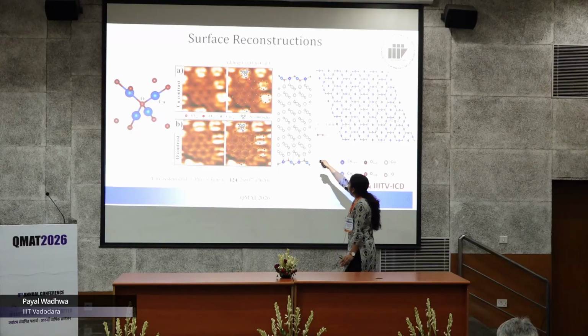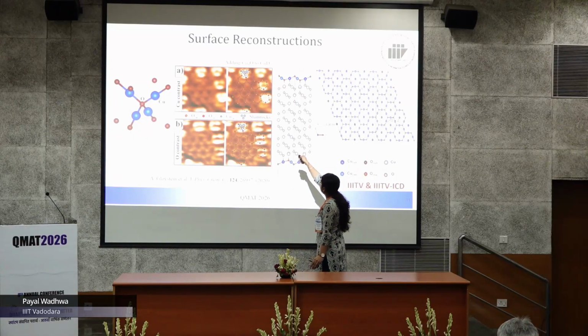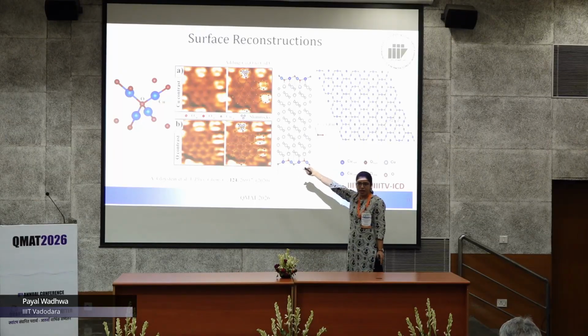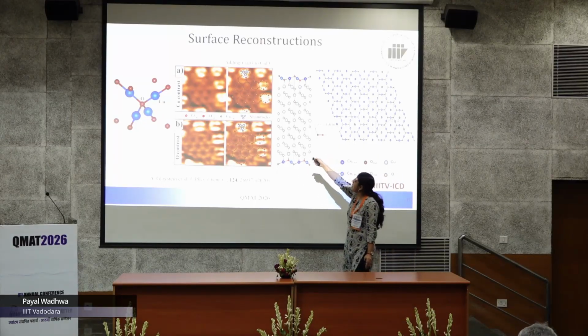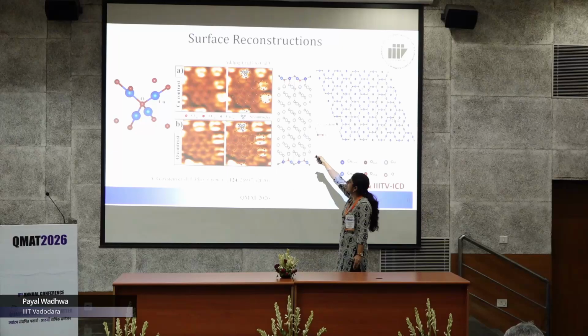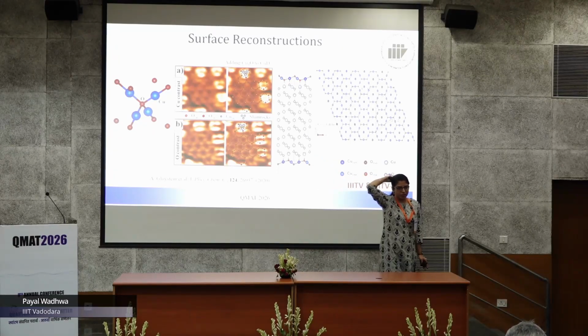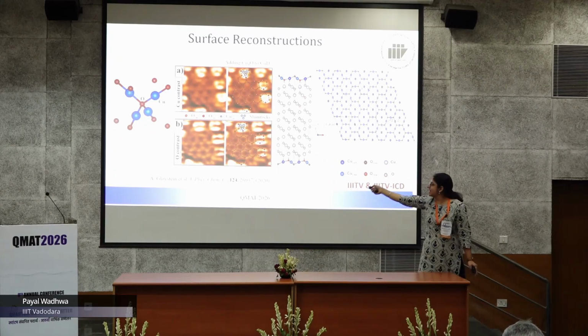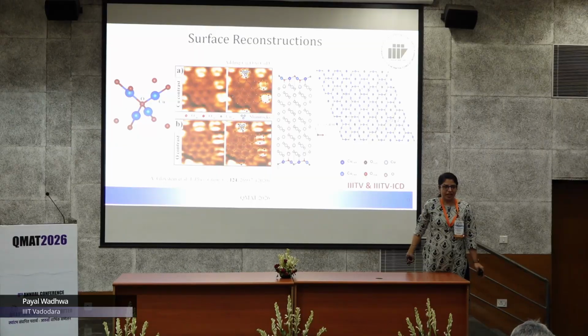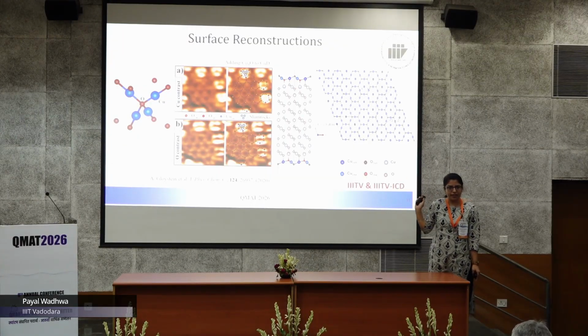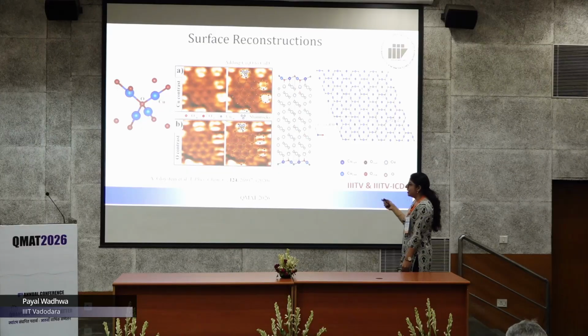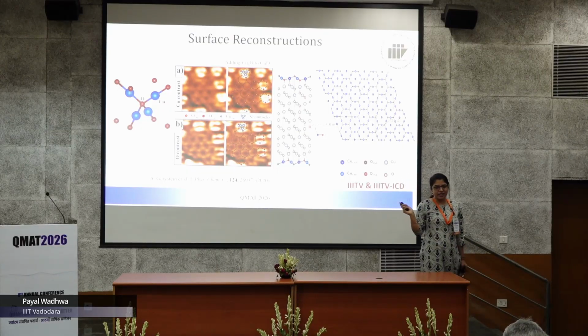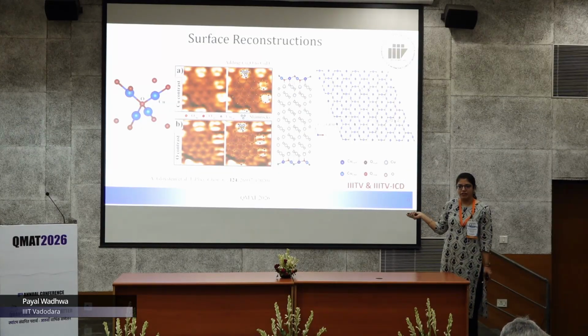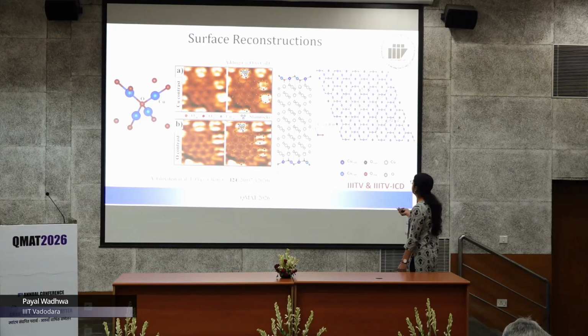But what you can see here in experiments, what they found is there is a copper cluster in the middle of this. And previous studies have said that this is by adding a Cu4O cluster into a copper deficient system. So of course, this system is not easy to predict using DFT, right? You need to make a lot of hit and trials to predict this structure, right? So, can we find an easy alternate? Let's see if on-the-fly training can help.